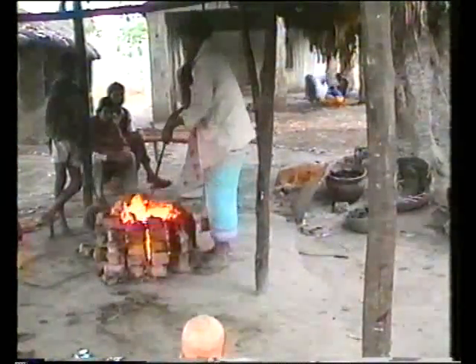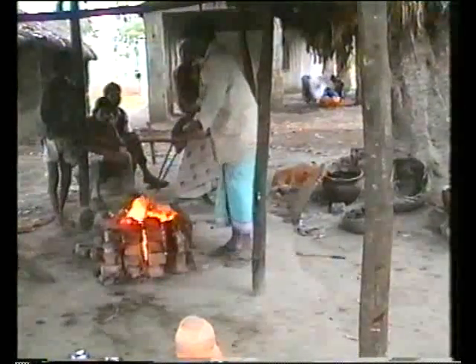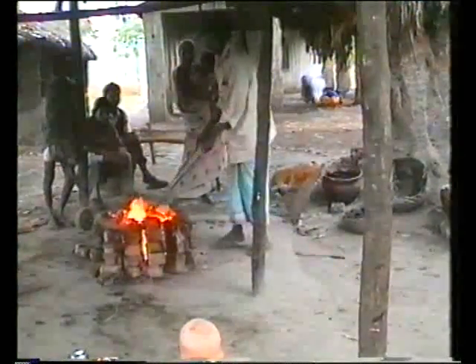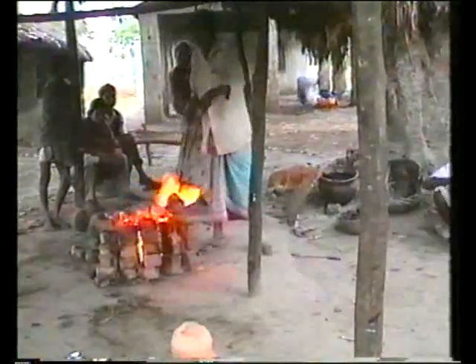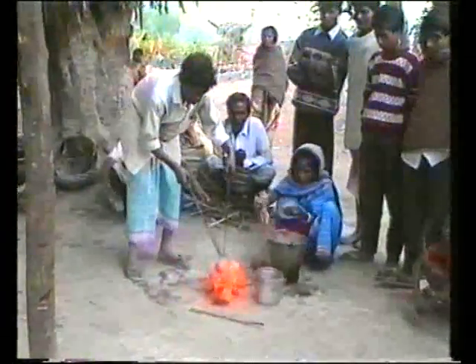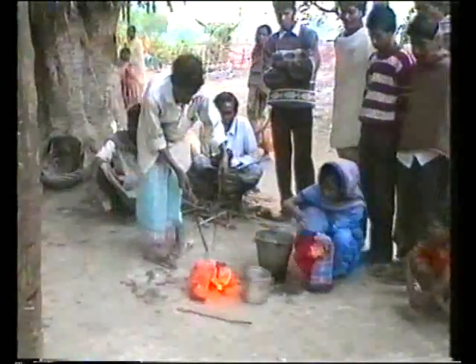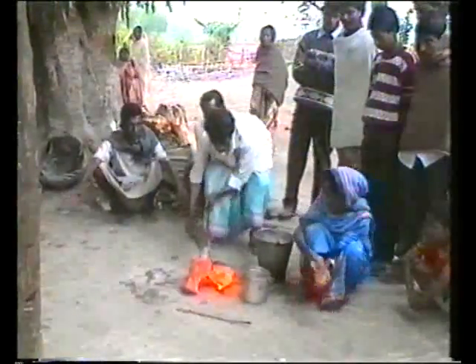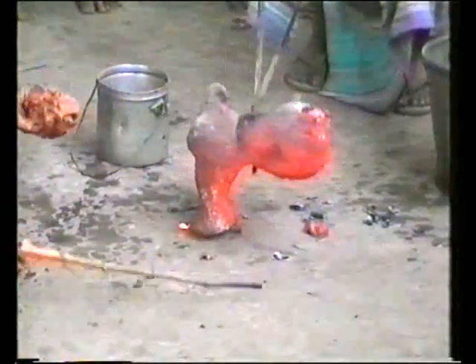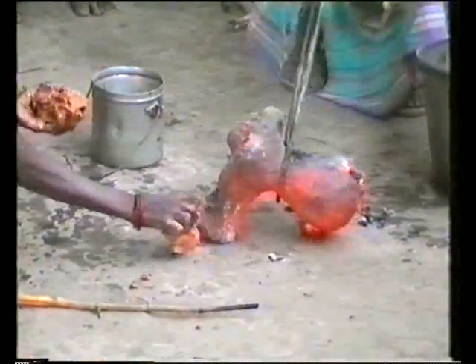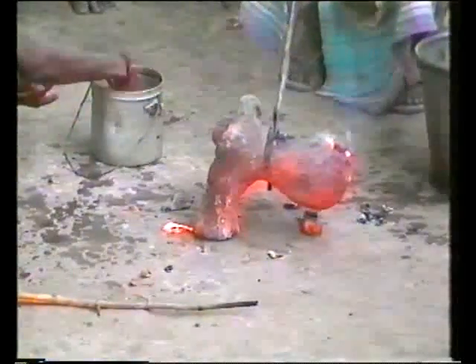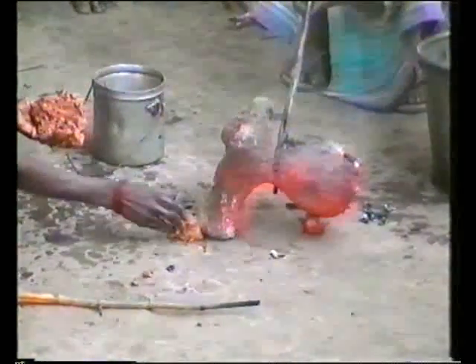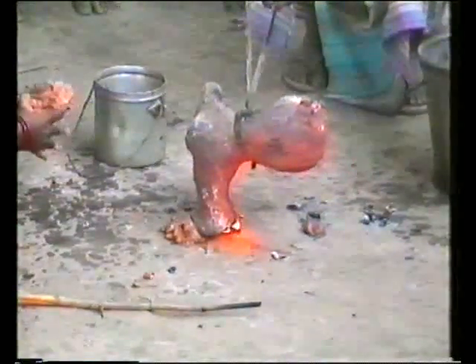Once the worker has decided that the molten metal is ready to pour, the red-hot mould is removed from the furnace. On hand is another worker with a bucket of water and some very moist clay to seal any cracks which may appear in the investment. When this does happen, the wet clay instantly hardens the molten metal and seals the leak.